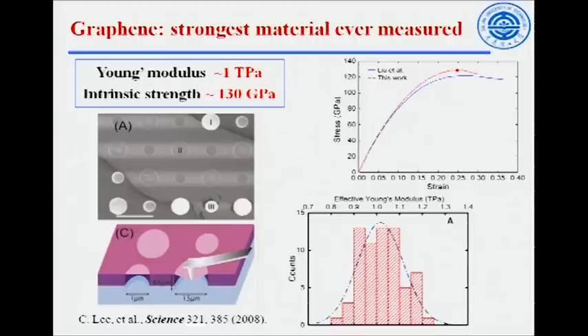This is an experiment from 2008. It was reported that the Young's modulus is as high as 1 terapascal, and the intrinsic strength, which normally we calculate but cannot measure directly, is as high as 130, which agrees excellently with ab initio calculation. So this is a very important system as an ultra-strong material.